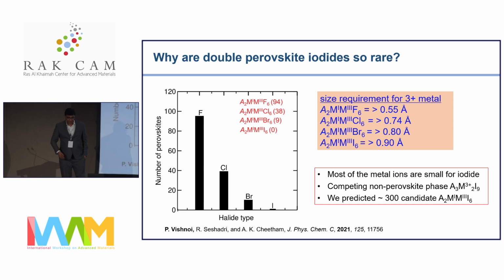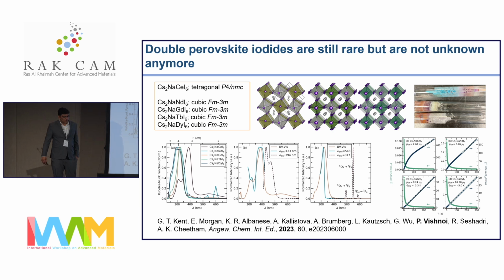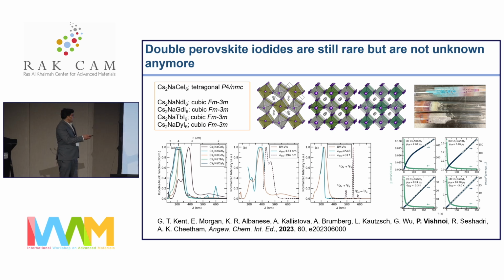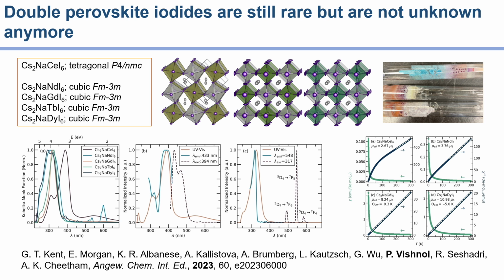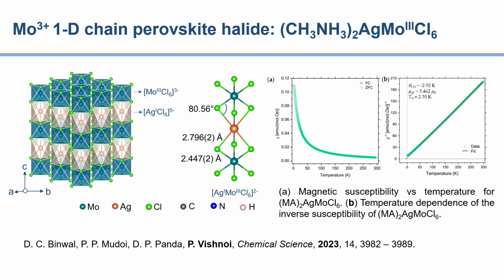Based on this calculation, we also predicted close to 300 structures, including metals which have a radius of 0.9 angstrom or above. And today, iodide perovskites are still rare, but they're not unknown anymore. About a year ago, last year, we reported 5 new structures, and I'm co-authoring the paper. These are basically based on f-block elements. And after working on this, we realized that iodide perovskites are even more difficult to make than we knew sometime before this paper appeared online. Okay, and here again, you see this compound.